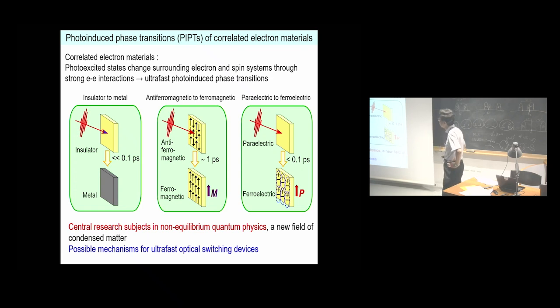As you know, the photoinduced phase transitions of correlated electron materials have attracted much attention. In those materials, photoexcited states change surrounding electron and spin systems through strong electron-electron interactions, which may give rise to ultrafast photoinduced phase transitions. So far, various phenomena have been discovered, such as the photoinduced insulator to metal transition, antiferromagnetic to ferromagnetic transition, and paraelectric to ferroelectric transitions. Those phenomena are attracting interest as a central research subject in non-equilibrium quantum physics, a new field of condensed matter, and also as possible mechanisms for ultrafast optical switching devices.